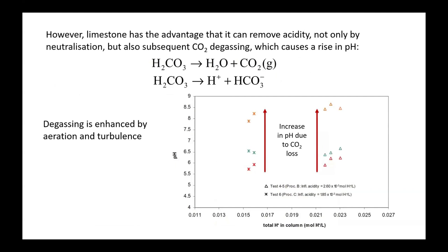However, before talking about ways of trying to minimise that precipitation of ferric hydroxide, I just want to point out that limestone has an additional advantage. So when it reacts with the acidity, it forms carbonic acid. And carbonic acid will break down to water and CO2 and give off the CO2 to the atmosphere as CO2 degassing. And by doing that, it actually uses up H+ by reversing the bottom reaction that we've got there to form carbonic acid to replace the carbonic acid that's lost due to CO2 degassing. We use up H+.